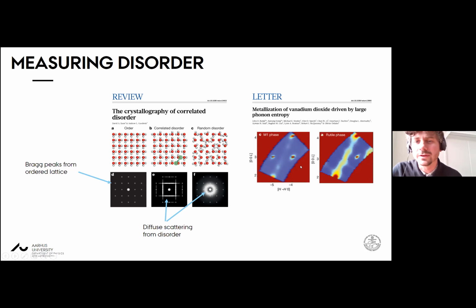And so there are two key things we want to look for. We want to look for the loss of the Bragg peak, which is this guy. You see this guy here is a monoclinic Bragg peak, which only appears in the low temperature phase. It's not there in the high temperature phase. There are some Bragg peaks which are present in both phases. So you see those. And then these are the stripes of diffuse scattering, which we want to look for in the transient response.